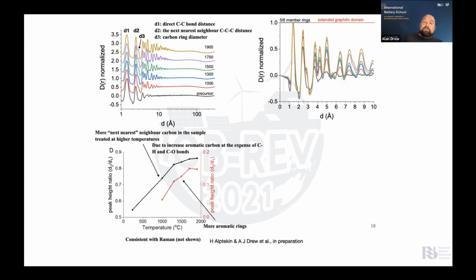If we plot ratios of amplitudes, you can see amplitudes are changing here. If we plot the ratio of amplitudes as a function of temperature, you can immediately see that this one here, which is D2 over D1, so CCC over CC, okay, is increasing as you increase the temperature. In other words, there are more next nearest neighbors in the carbon treated at higher temperatures.